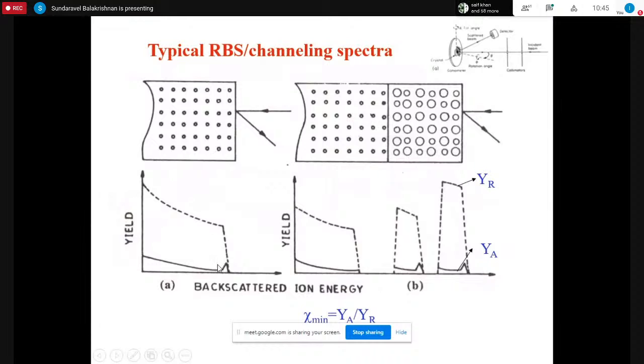And we can find the crystallinity of the crystal from the ratio of the backscattered yield in the channeling spectrum to the random spectrum. That is called chi minimum. It is a measure of crystalline quality, Ya by Yr. So for very good crystals, this chi minimum value will be within 3%. That means that if 100 particles are getting scattered in a random direction, in the aligned direction only less than 3 particles will be getting scattered.